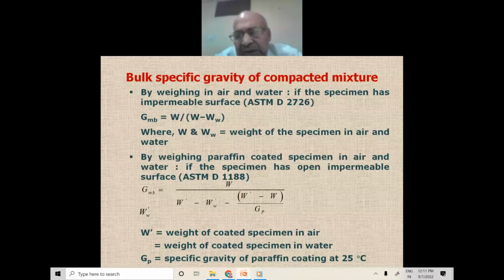At least 3 specimens shall be prepared at each trial bitumen content, which may be varied at 0.5% increment. Similarly, at least 3 specimens shall be prepared for each trial plastic waste content. This is the composition of a Marshall specimen, which comprises plastic waste coated aggregate, bitumen, voids, fine aggregate, and the mineral filler.